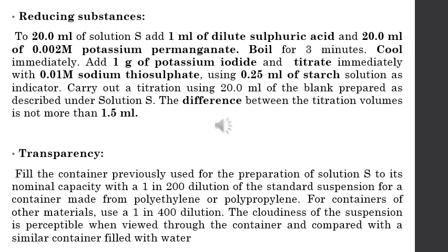For transparency, we have to take standard suspension and dilute it to 1 in 200 dilution, if we are using a polyethylene or polypropylene type of plastic as a container, and if it is other plastic, the dilution is 1 in 400 dilution. The cloudiness of the suspension is viewed through the container, and it is compared with the container which is filled with water.